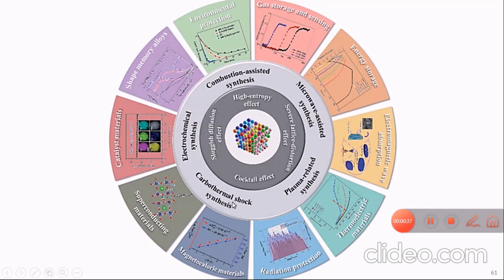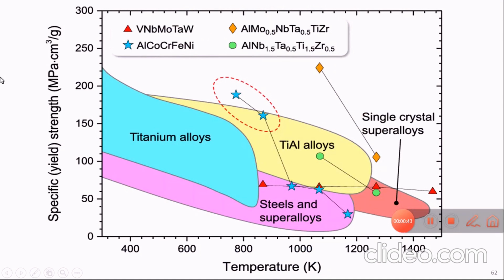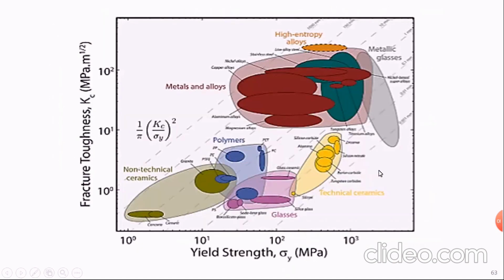All of this is because of its four core effects, which give it special properties and special applications. Here, if we look at the specific strengths with temperature for high entropy alloys, the first application that comes to our mind is the aviation industry. Some parts in the aeroplane should keep strength at high temperatures. That's why high entropy alloys are favorable in this case. Some applications need high fracture toughness while keeping good yield strength. If we look, we can see that high entropy alloys are on the top of the alloys to do so.